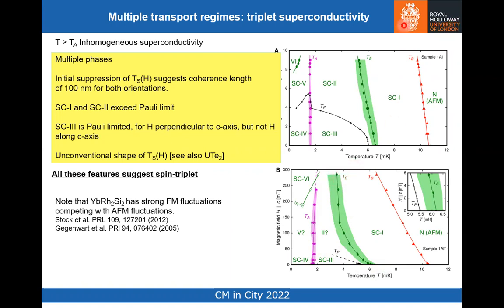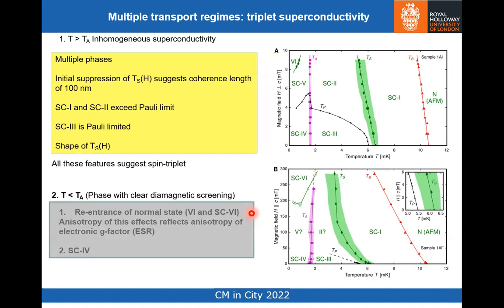Anyway, this multiplicity of transport regimes, and the behavior of the critical field, all suggest spin triplet pairing. And maybe that's not so surprising, because YbRh2Si2 has strong ferromagnetic spin fluctuations, which are competing with the antiferromagnetic spin fluctuations, and ferromagnetic spin fluctuations would definitely stabilize spin triplet.